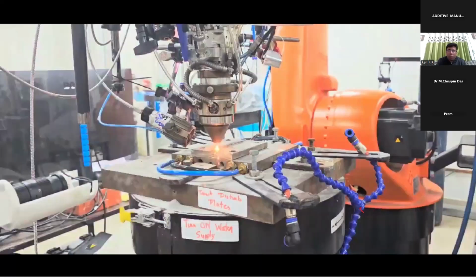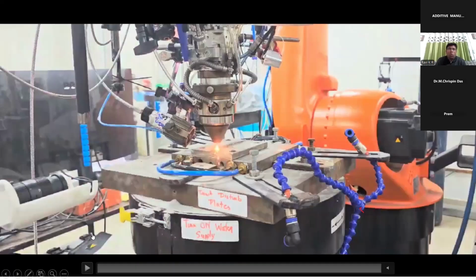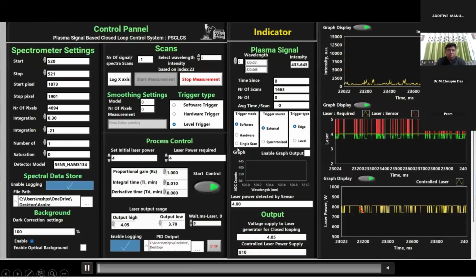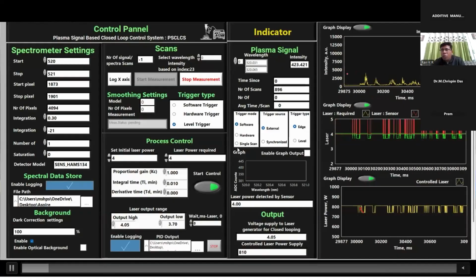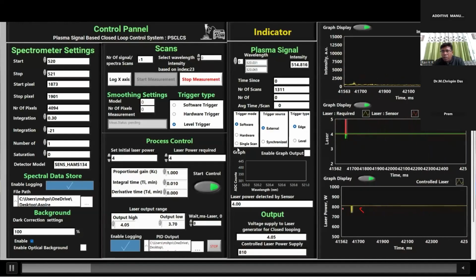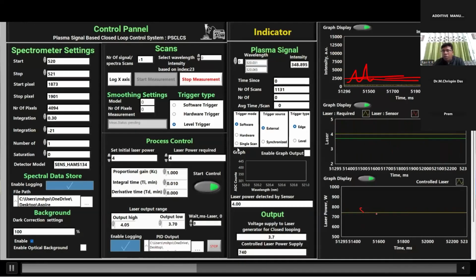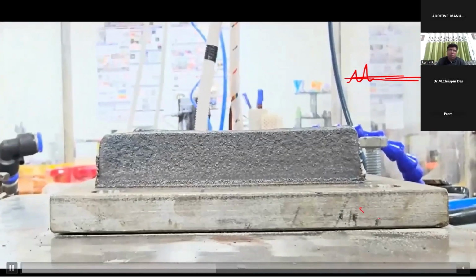Now we have developed hardware and software for closed loop control, which means now I'm going to control the process. You can see here the intensity I'm getting without any control. In this case, I'm controlling the laser power. Whenever the intensity goes up beyond a threshold, like what we do in a furnace, I keep that value down by decreasing the laser power.